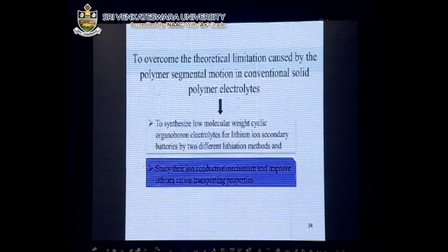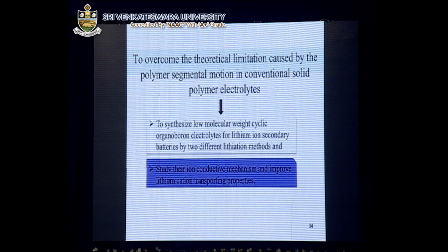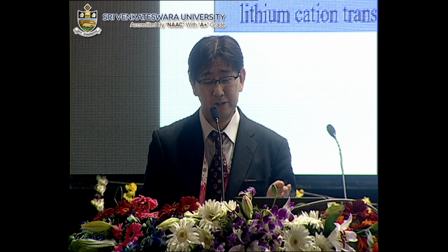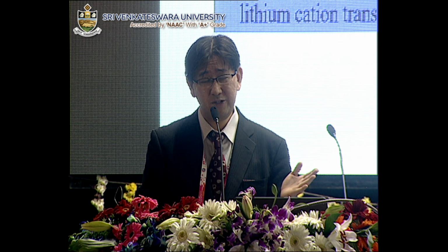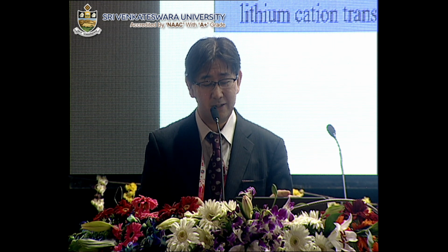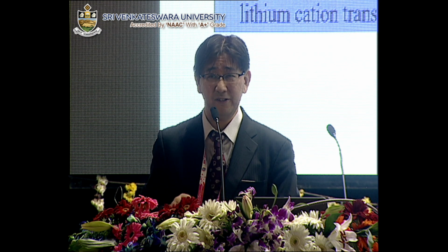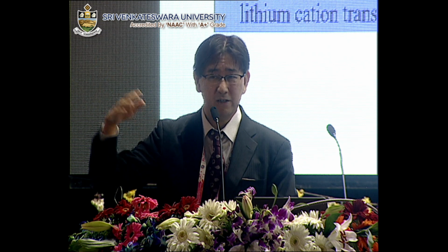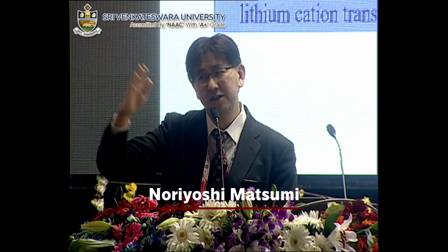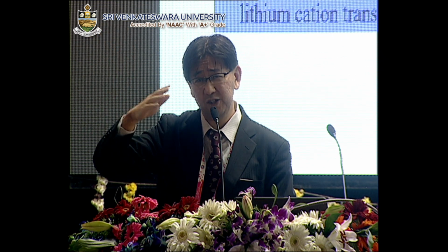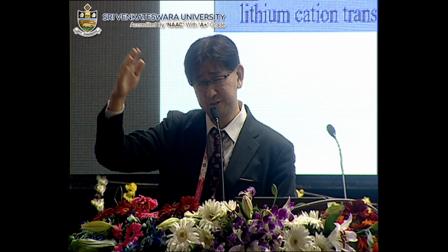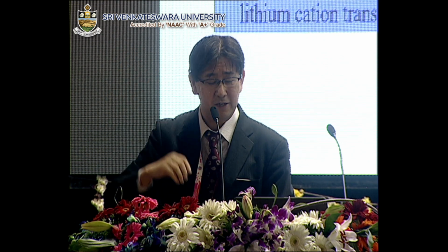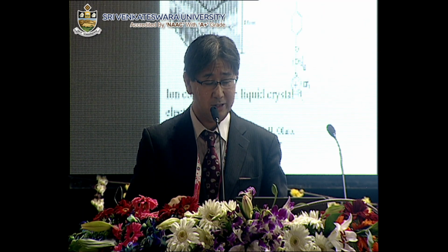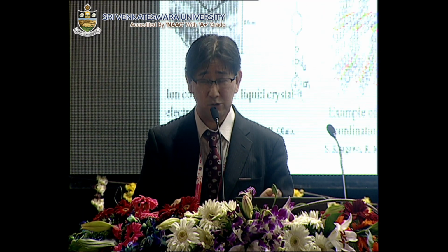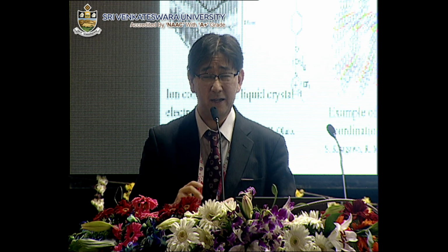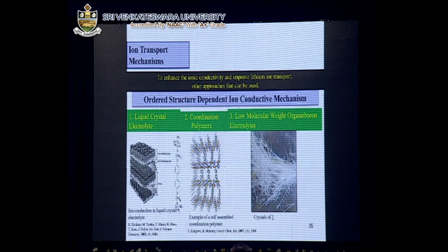And nowadays, in the field of solid polymer electrolytes, many researchers have pointed out the theoretical limitation of their ionic conductivity. They say that as long as the ionic motion depends on the segmental motion of the polymer chain, such ionic transportation can never exceed the diffusion rate of its low molecular weight counterpart. So many researchers are trying to facilitate ionic transportation in the solid state by introducing some structural order to ion conductive pathways.